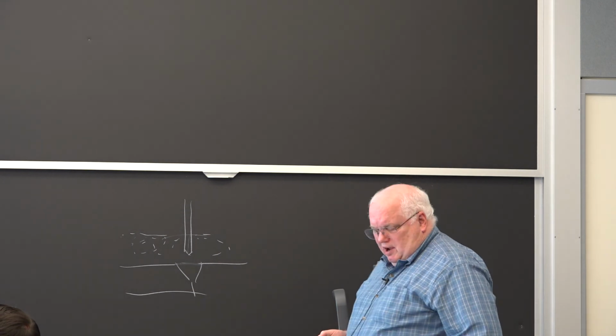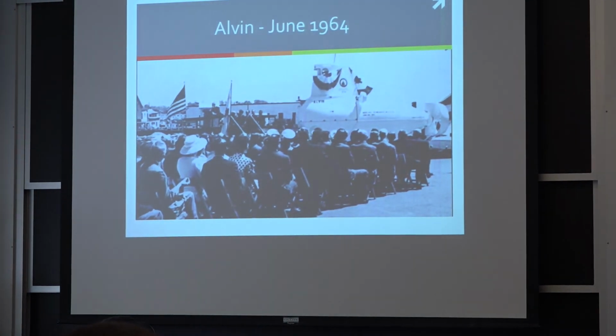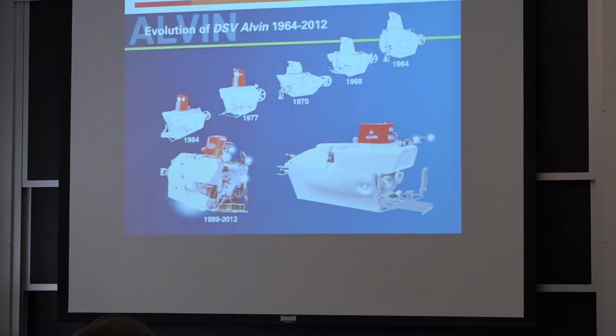Here's the '64 Alvin. You can see a couple of white caps there in the audience. As the Navy paid for it, it was a steel hull originally. Somewhere around 1970 or so, they switched it out to a titanium hull. And that was partly because the Navy was trying to build their expertise up with titanium. And I'll tell you another story about the Seacliff, which was another Navy submersible.